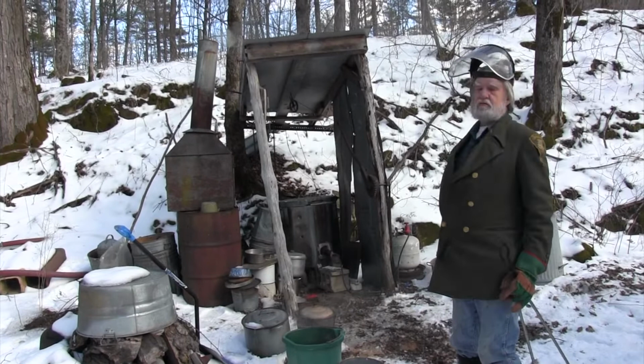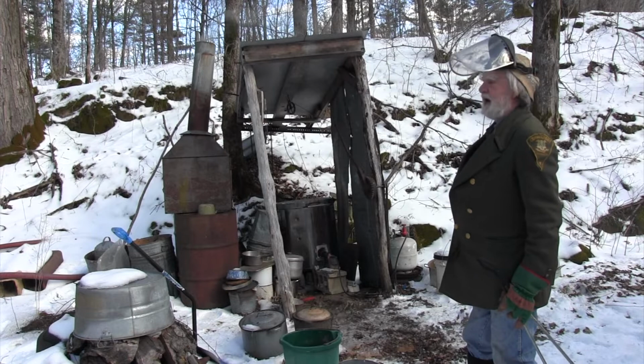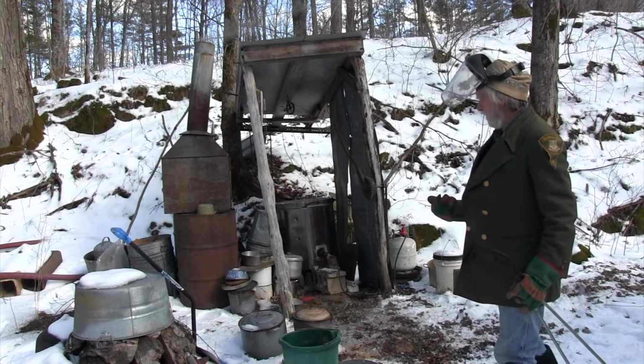And then I have 2 buckets of water that I'll immerse them in slowly. And so I don't trap air, I don't flip them over. I've got to come in bottom side down. If water comes in, it needs to come in so the steam will go up. Because if you had it fall over and go in sideways, it's going to burst your piece because the steam will get trapped.